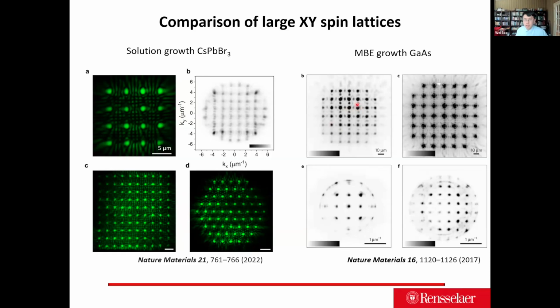So this experiment has recently been done with the gallium arsenide, but just to show you the sample quality, we decided not to do any feedback, to compare with the original result with the MBE-grown gallium arsenide to show the superiority of our room temperature sample. Just with a solution process, you can get an almost identical sample, identical physics result without bothering with MBE.